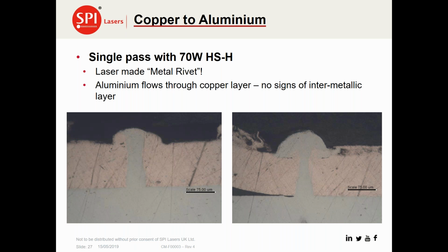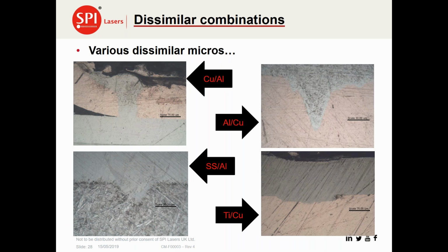What's interesting, however, is this process actually differs depending on the materials that are used, and indeed the order of the materials, which one is on top. For example, here are some more examples. On the top left, you have copper and aluminium, as you've seen in the previous slides. But also on the right of that, you see aluminium to copper. So this is reversed, and you can actually see there's a very different structure here. The one on the left shows flow of aluminium up through the copper itself. The one on the right is actually more like a staking process, where you're pushing material from above into the material below.